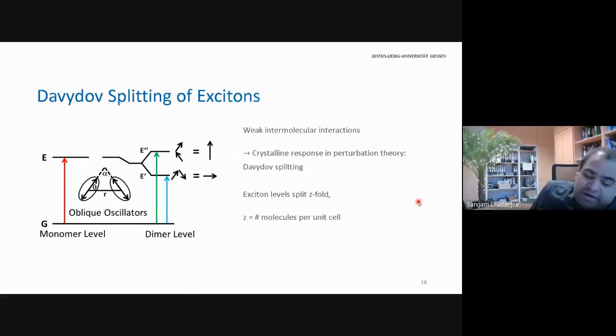Now, this concept of delocalization and interaction of molecules is actually fairly old. There is a concept called the Davydov splitting of excitons, a picture introduced something like 50 plus years ago, which says that if you have two molecular dipoles and they're coupled, you will get a splitting in the resonance. This is basically a very simple picture of vector addition. You have two transition dipole moments, and you can add them if they're at an angle. You get a resulting dipole moment along, let's say, the horizontal direction as indicated here, or along the vertical direction as indicated here.